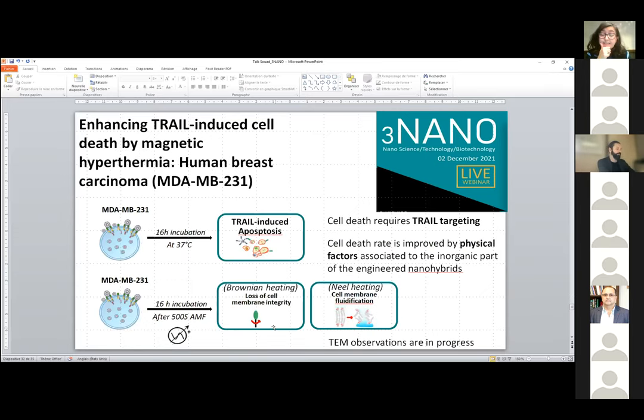So our idea is that when TRAIL is attached to its receptor, and TRAIL, of course, is attached to the magnetic particles, when we apply the magnetic field, we have Brownian motion. That means the particles can move, but they are attached to the cell membrane. So they can break the cell membrane, and we lose the membrane integrity and the cell dies. Or also, these particles, when you apply the magnetic field, may heat, and the proximity of the particle to the cell membrane makes this heating high enough to induce cell membrane fluidification. And once again, loss of the cell membrane integrity and cell death.